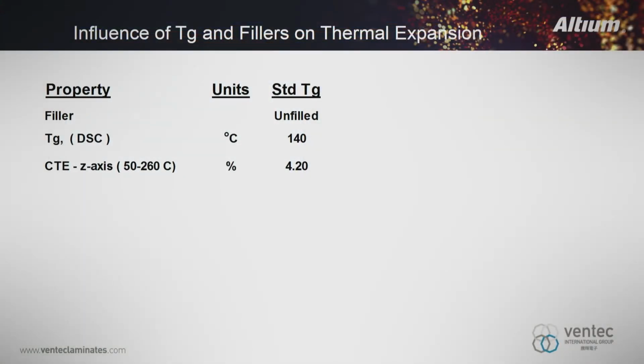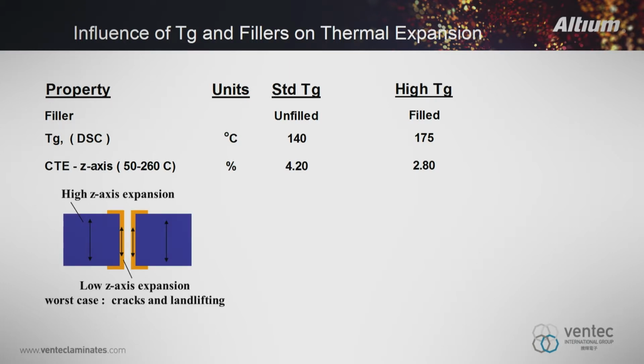I mentioned before we can use resins or we can use mixtures of resins or different materials in there. The standard was to use what's called unfilled, just basic epoxy resin. But we can put things in there that have a lower CTE. So we can mix in ceramics and we can actually make this expand at a lower rate. So we can take a material and actually put some filler in instead. Actually, there should be a third one in there. Okay, it doesn't matter. So we can take the TG to 175, and if we put a filler in there that expands at a lower rate than the resin, we can get down to around 2.8% between 50 and 260 degrees centigrade.